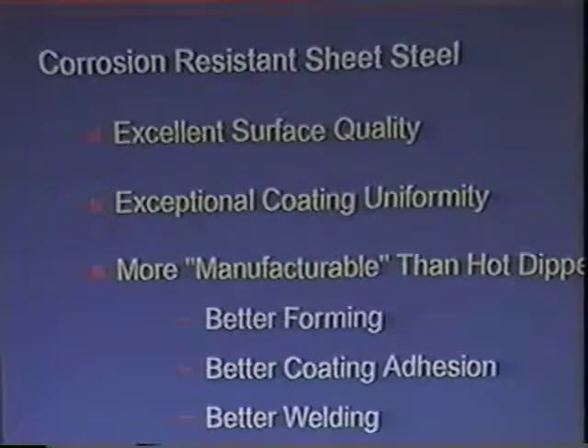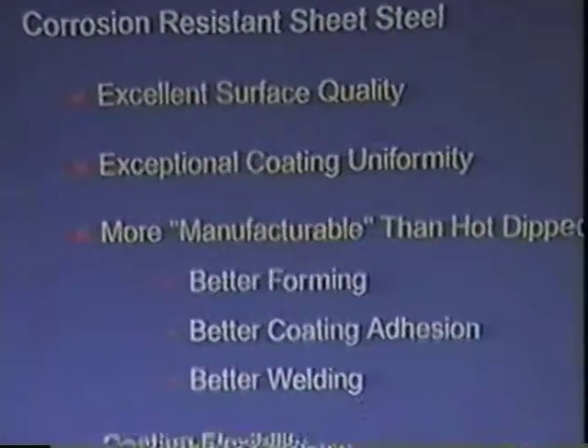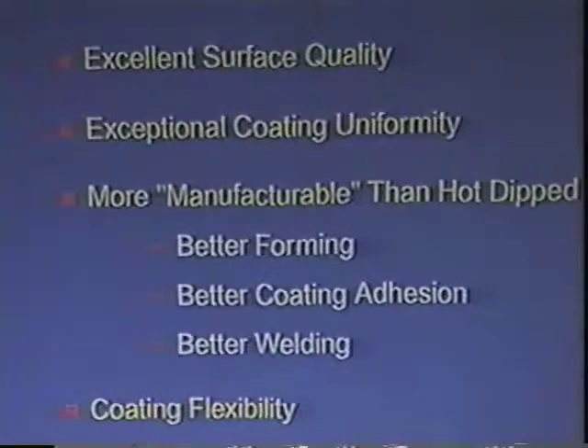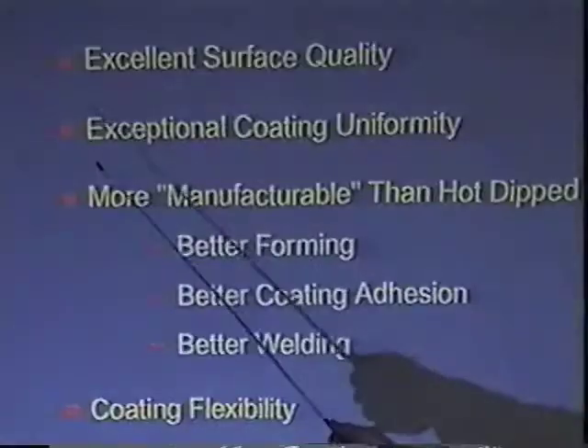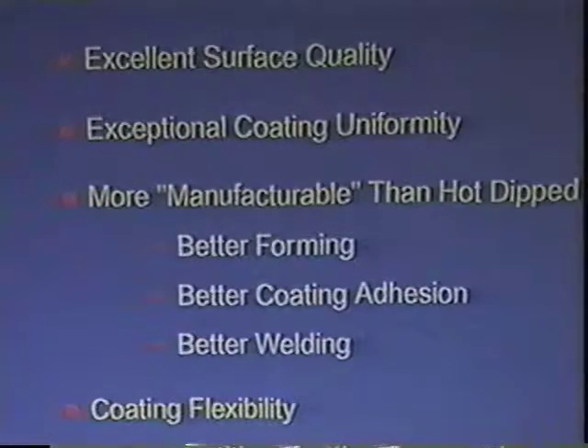Excellent surface quality. It's only as good as the surface quality going into it. So if you have an excellent surface quality coming out the temper mill, when you electrogalvanize, you'll mimic that surface. So if it's a good quality, this won't make it any worse, hopefully, unless they have a problem coating it. But it should mimic that. So if you have a good surface coming in, you'll have a good surface going out. It should be the same type surface, the same roughness, the same look to it, all that kind of stuff.